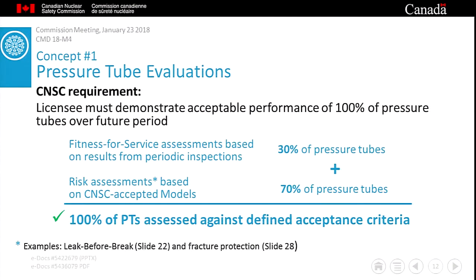At this point, it's important to distinguish between the two types of pressure tube assessments that CNSC staff review. First, assessments that are done to confirm that inspected pressure tubes are fit for continued service. In accordance with their license condition handbook, a licensee is obliged to conduct periodic inspections and compare the results against CSA acceptance criteria. If the inspection finding does not meet those criteria, the licensee must submit a fitness for service assessment for the inspected pressure tube for CNSC acceptance. These assessments cover approximately 30% of the pressure tubes in service in Ontario.